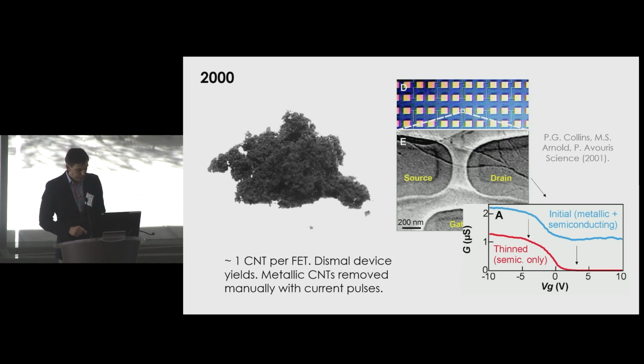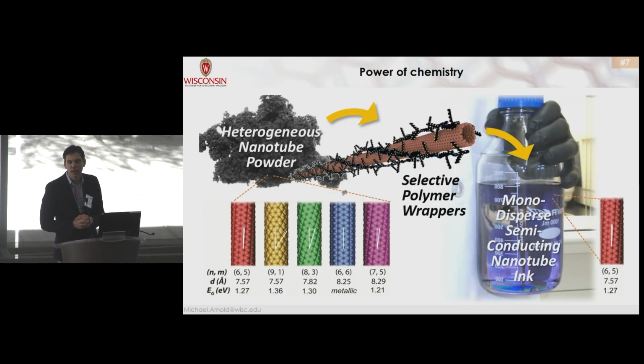And the other thing about this powder is that not only is there a lot of soot in there, but among the nanotubes, there are different types of nanotubes. There are metallic nanotubes and semiconducting nanotubes, and we want just those semiconductors. So some of my first work on nanotubes was taking a bundle of nanotubes that had both metallic and semiconducting ones and using pulses of electricity, transistor by transistor, to burn out the metallic ones to get just the semiconducting ones crossing the channel. So back in 2000, the field was super primitive. But it's undergone a huge transformation in the last 20 years.